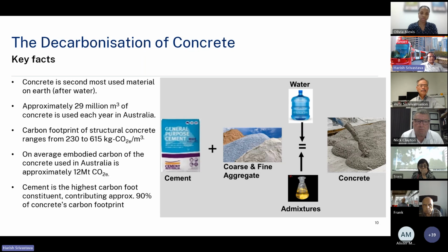And if we look at the picture on the right, out of all these materials, Portland cement is the highest emitting material in concrete. Though we use only 12 to 15% of cement in concrete, it is responsible for about 90% of the CO2. That's why most of the strategies revolve around eliminating or reducing Portland cement.